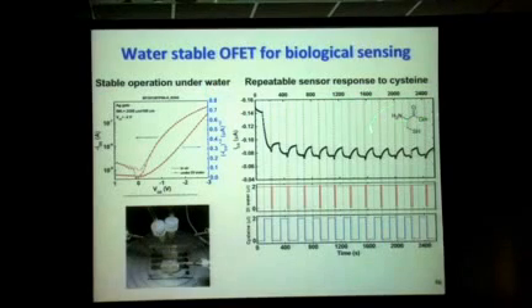If you add some analytes to the liquid, you can have changes in the electrical characteristics, but the important point is it's fully reversible - there's no degradation of the transistor, as opposed to a lot of the sensor work done in the past, where the transistor was used as a sensor because it was degrading in contact with oxygen and moisture.